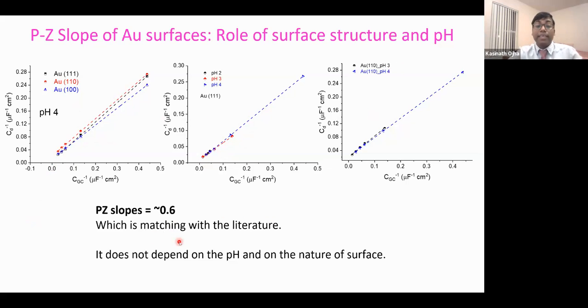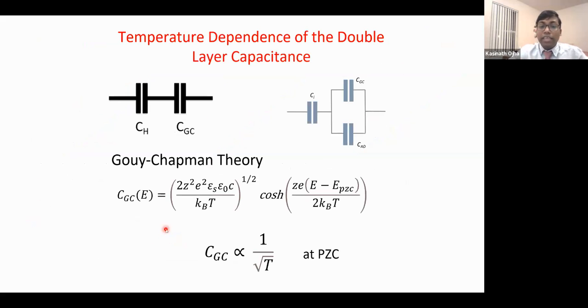So the thing is, I showed it doesn't depend on the ions, doesn't depend on the pH, and doesn't depend on the nature of the surface. So let's look at the equation again. This is the Gouy-Chapman theory equation, and it depends right at the PZC. When E equals E_PZC, this term is 1, and then only the Gouy-Chapman capacitance is proportional to this. If you look carefully, the Gouy-Chapman capacitance is proportional to 1 by square root of temperature. Now if we do different temperature measurements, that has to be linear with 1 by square root T.